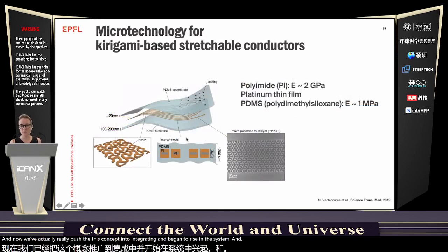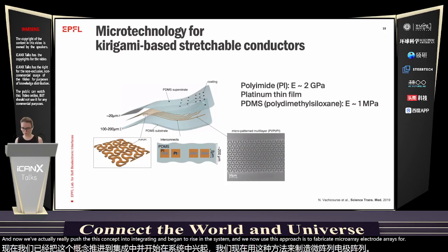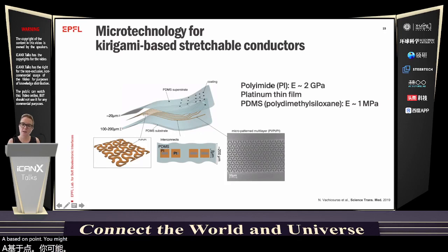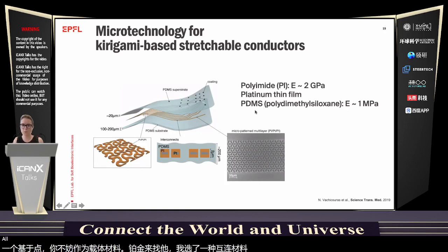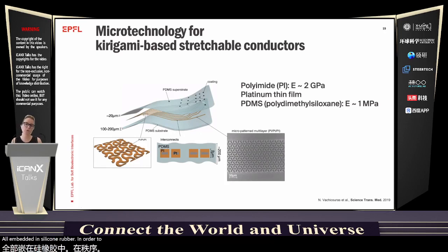And now we've really pushed this concept into integrating and miniaturizing this system. We now use these approaches to fabricate microelectrode arrays for some of our bioelectronic applications based on polyimide as a carrier material, platinum film as electrode and interconnect materials, all embedded in silicone rubber in order to form microstructures, but yet fully elastic stretchable conductors and electrodes.